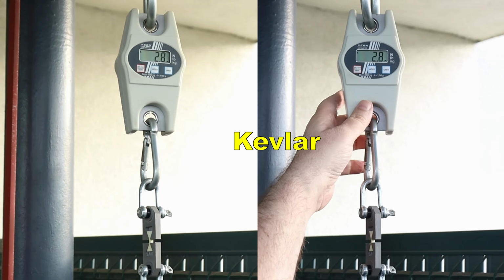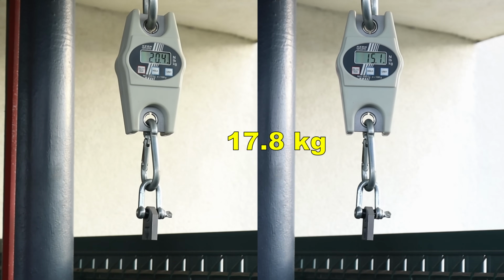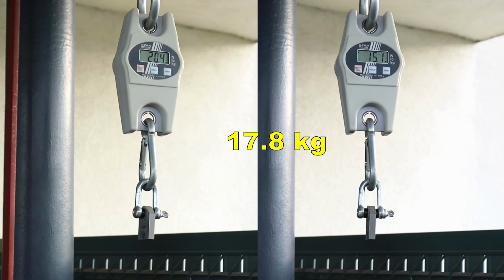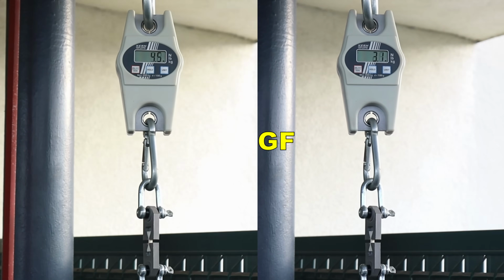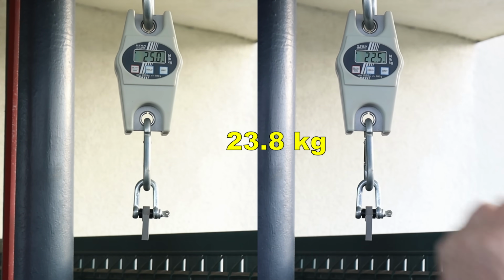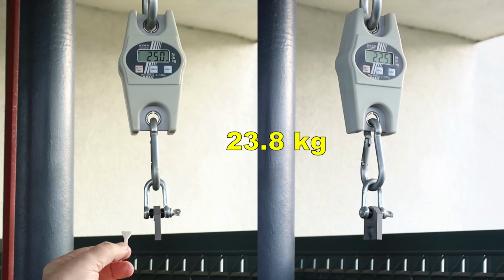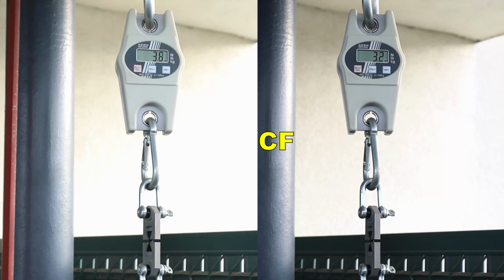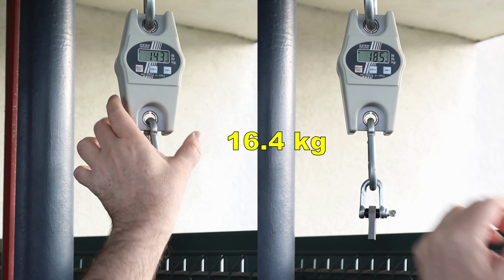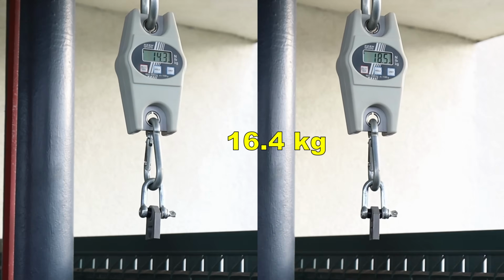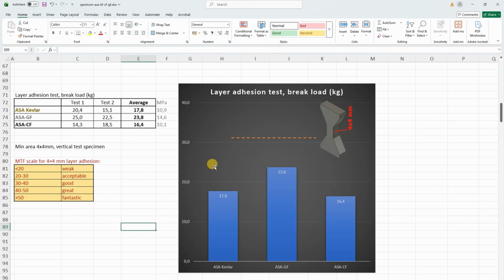Layer adhesion, Kevlar. These objects are printed in vertical position. Glass fiber version. Stronger a little bit. Carbon fiber version. This is also very weak. According to my rating, the Kevlar and carbon fiber versions are quite weak, the glass fiber acceptable, but in all three cases they are far below this line, average ASA, of course without fibers.